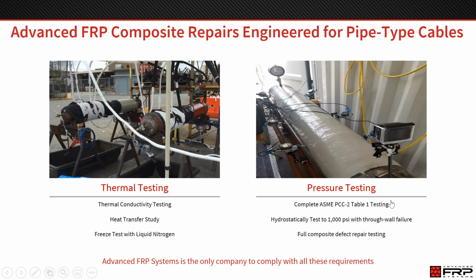We did thermal conductivity testing of the composite itself to be able to model how heat would flow through it. And then a full heat transfer study was performed on an underground power line with a carbon fiber composite on it. We wanted to ensure that we were going to allow heat to dissipate through the system, even with large scale composite repairs. We also wanted to do something called a freeze test.